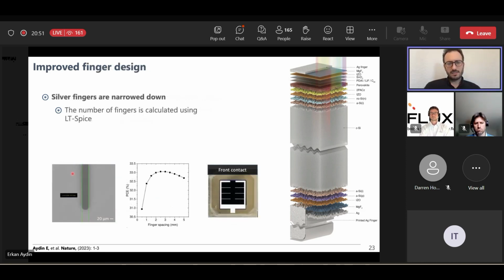The other contribution is also, for sure, from the front contacts, because if you use a resistive TCO, then you have to put more fingers for efficient charge collection. In this case, we also had to optimize the number of fingers and their distribution. And we maximized the power conversion efficiency by just tuning the fingers.